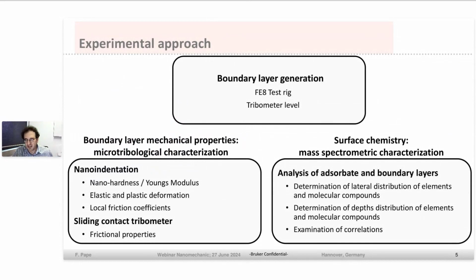So these investigations give us information on the boundary layer generation. We can investigate the frictional torque during the test and afterwards investigate the tribofilms directly in this FE8 test rig. And of course, we can also work on tribometer level to investigate the film formation on tribometers, but also to investigate the tribofilm by tribometers after the test.